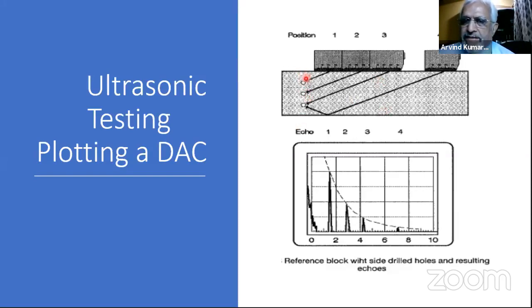One is at T by 4 thickness, another is at half thickness, and the other is at 3T by 4 thickness. So what we do is change the probe position. This is probe position 1, 2, 3, and then it has gone like this. At 1, it is hitting the first hole. At 2, it is hitting the middle hole. At 3, it is hitting the bottom hole. And at the fourth, it is hitting the bottom hole after a bounce.